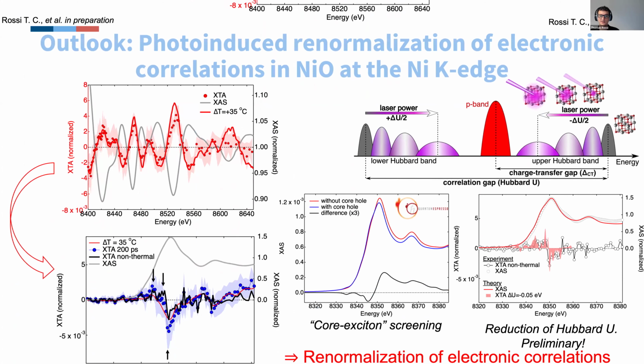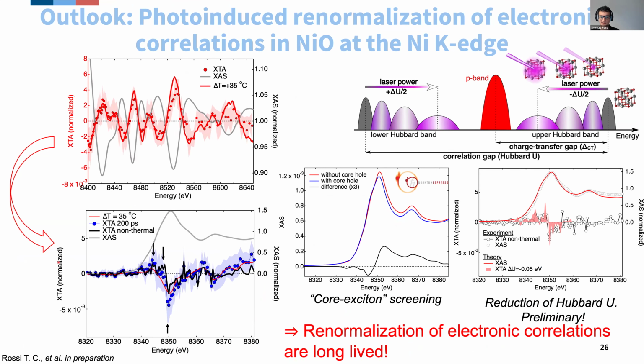And we use this information again in the XANES. So starting from the EXAFS, going into the XANES, we can take the difference between the pump probe data and the simulation from lattice heating. And the difference we get is the black curve. That is noisy, but there is a little bit of a signal that you can see with some positive signal here at the rising edge and some negative signal here at the white line.